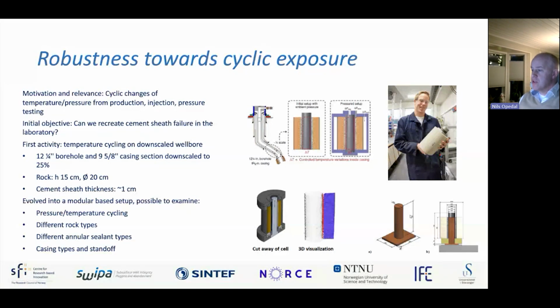So the figures here show, at least in the central bottom part, a cutaway of one of our cells, showing again how the specimen is located inside a cell, enabling us to cure the cement under pressure, for instance. They are also CT transparent, so the wall is made of either aluminum or carbon fiber, enabling us to visualize them in CT. The 3D visualization shows an example of what it can look like, where the red indicates a fracture in the cement sheath, and the purple-blue indicates fracture in the surrounding rock.